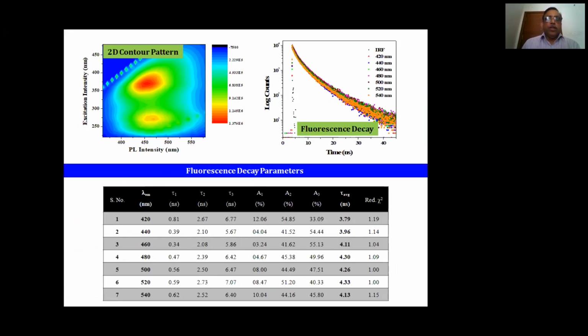Now we also did contour analysis to find out the multi-components present in this material, and the fluorescence lifetime analysis. You can see triple exponential lifetime, on the order of 0.8 nanoseconds, 2.6 nanoseconds. So it's multi-exponential we get from this material.